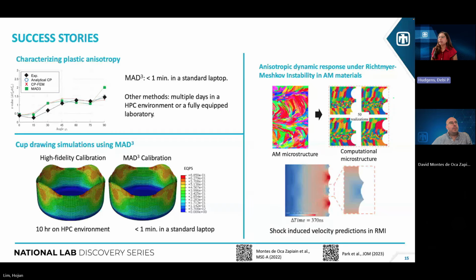And is MAD³ capable of elevated temperature simulations? As we mentioned before, these focus solely on the initial characterization of load-dependent behavior. That's what provides the calibration for the models. However, once you have the calibrated parameters, you can actually use those parameters to run simulations at higher temperature. One of those examples is the one that is currently on the slide on the right. In those, we used MAD³ to calibrate the yield models for these additively manufactured microstructures, and then we ran essentially shock simulations at high temperature and high pressure for these materials. So the model itself is usable for calibrating the load-dependent behavior of the materials. The resultant calibrated parameters can then be used for other applications.